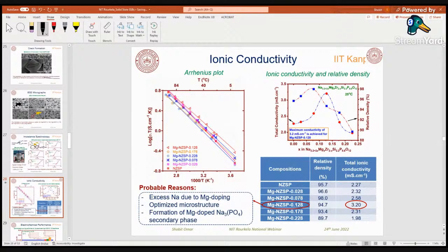So we plotted the Arrhenius plot, but this figure is important. You can see that conductivity increases with increase in the magnesium content, and then there is a decrease. This increase is because of the increase in the excess sodium amount in the material. Of course, the 0.128 composition has the optimized microstructure. It does not have any liquid phase, and there is negligible cracking. And of course, there is a decrease in the density, right?